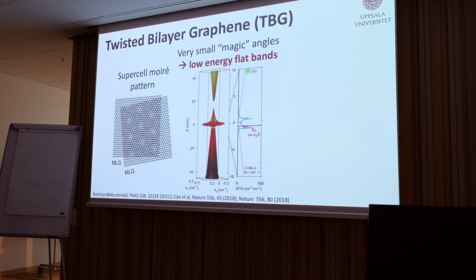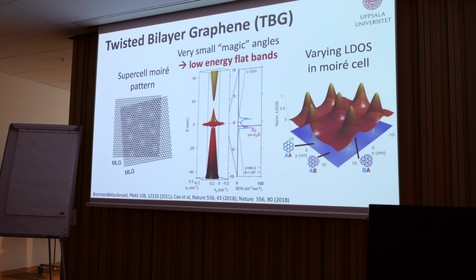So the graphene spectrum is here blown up 1,000 times. You see these are very tall peaks in the density of states. What's also important to keep in mind is that the density of states varies a lot in the Moiré cell. You have a very high density of states in the AA region and very low in the AB region. There are still some electrons in the AB region, but you have very pronounced peaks in real space in the AA region. That's going to be important because the superconducting state responds to where the carriers are. If you have a lot of carriers, that's where you get a lot of pairing as well.